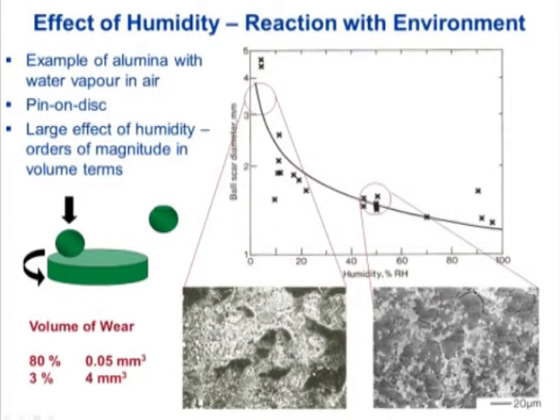And the reason for that is that at low humidity, as indicated here, the micrograph shows that you've got a lot of fracture going on, whereas at high humidity you've got this dark phase formed. We found that this was aluminium hydroxide, and it protects the surface. So there is a critical difference in the mechanism that you need to look at, which means that high humidity is much better in this situation.